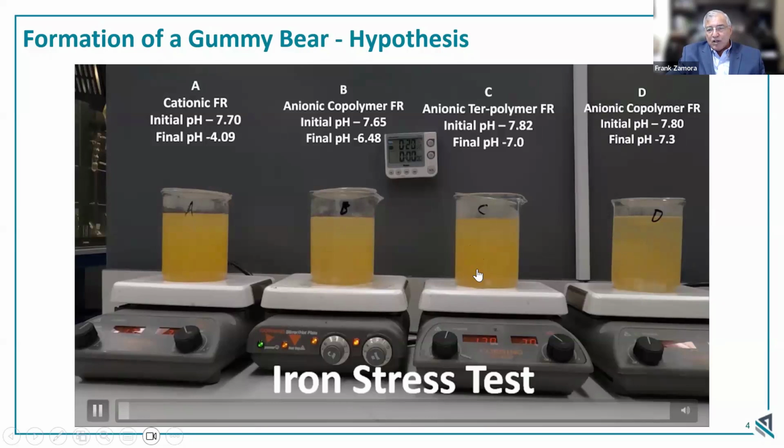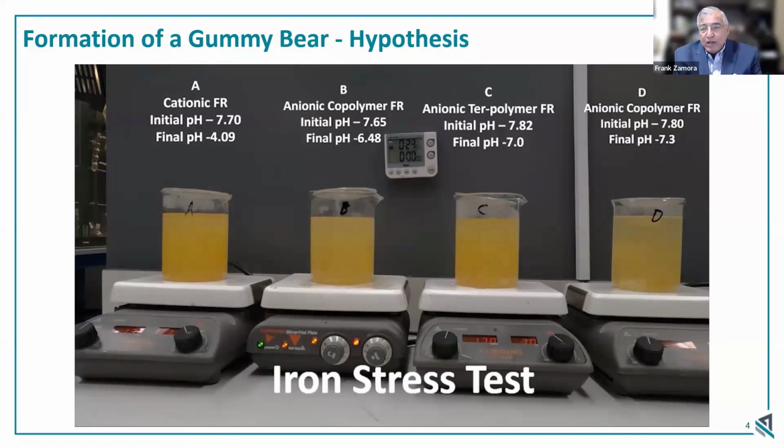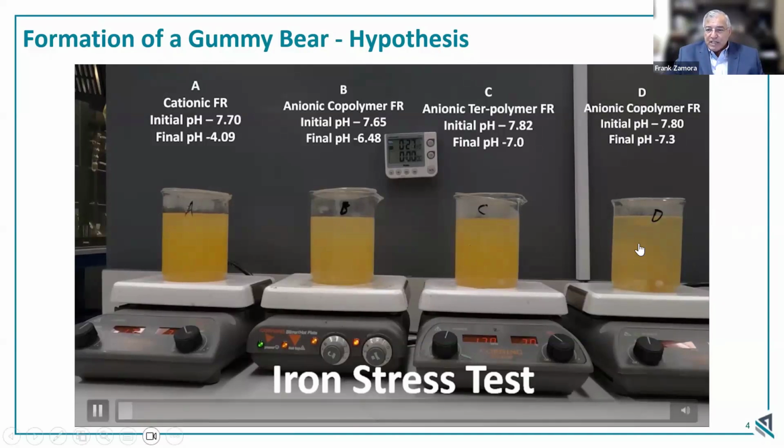We're not seeing much on the AMPS, and this is the beauty of the AMPS, in that you're going to precipitate an AMPS either way, but they're not going to agglomerate like the acrylates do. You can see very quickly that in a matter of 30 minutes, we've already started to develop this agglomeration of polymer.